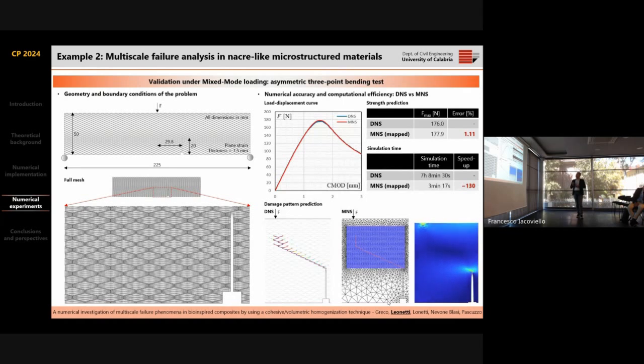And here, a mixed-mode bending test, the same test, but with the notch. Also in this case, the MNS and the DNS predict the same result. Also in terms of global crack path, you can see in the direct numerical simulation the path is this one, multiple cracking. Here, just the main crack predicted with the same angle. And the speed-up value is even higher, 130.